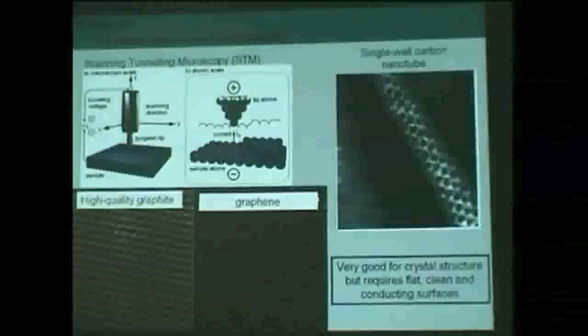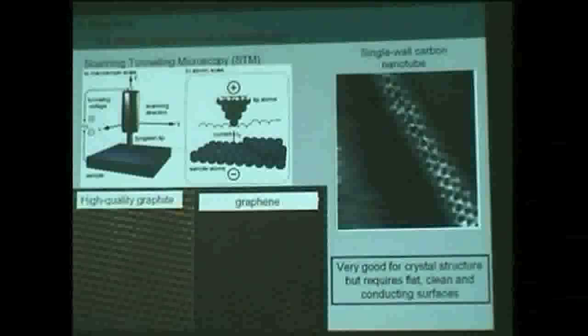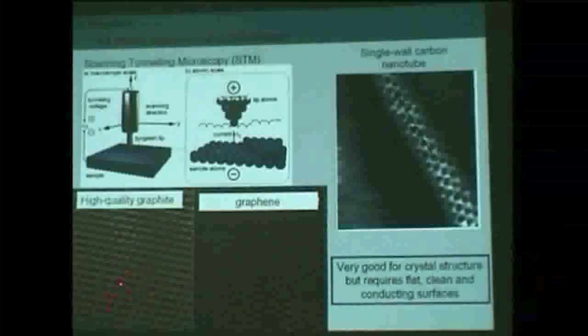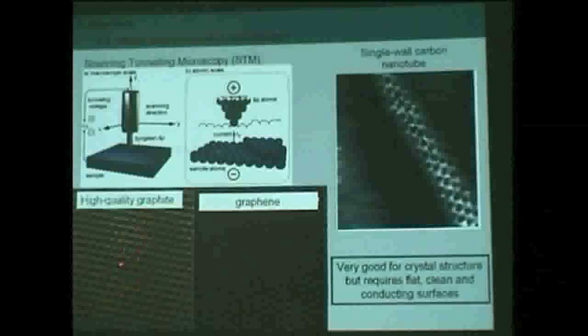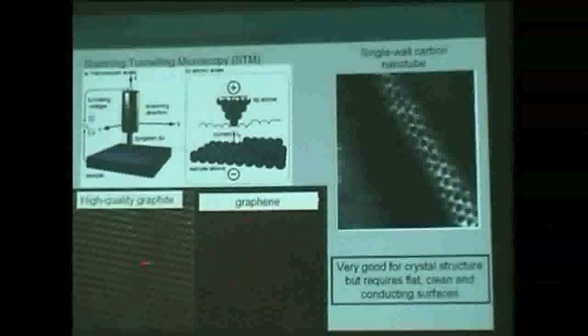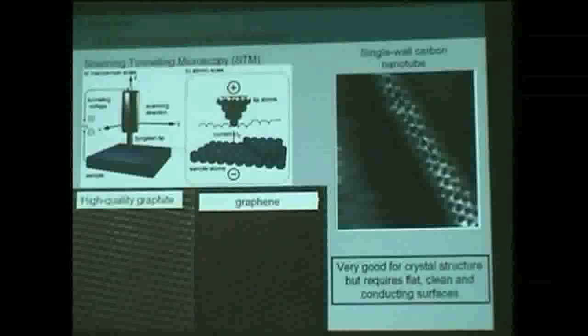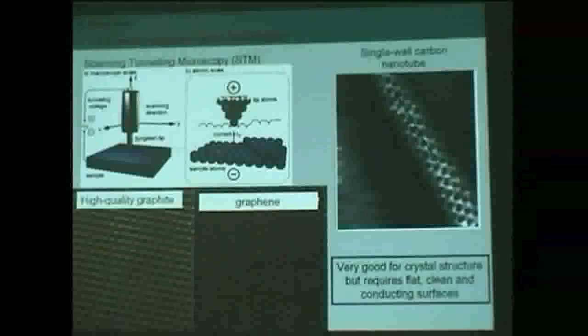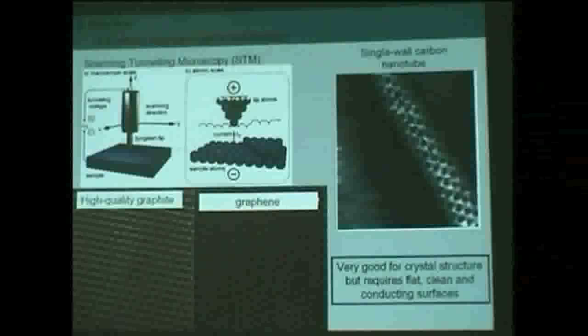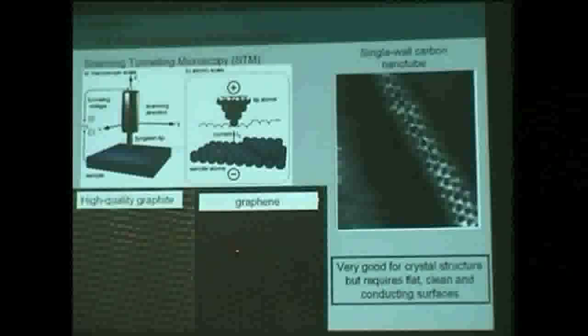If we apply that to graphite, we get this image which shows very nicely the sp2 bonding, the honeycomb lattice of the top layer of graphite, very similar to the case of graphene. We find those honeycomb lattices in both cases, which confirms it's actually sp2 bonding, giving this very flat honeycomb lattice in both cases.